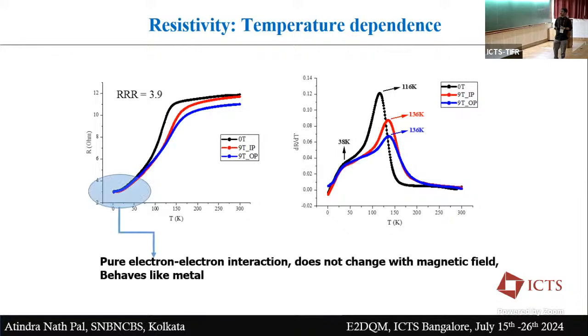So from this, we can conclude that this part is dominated mainly by electron-electron interaction, and it does not change with the magnetic field and behaves like an ordinary metal, right? But above this, you have a strong electron-magnon interaction, which is modulated by the magnetic field. So we can say that for this T square in this regime, electron-magnon is significant.